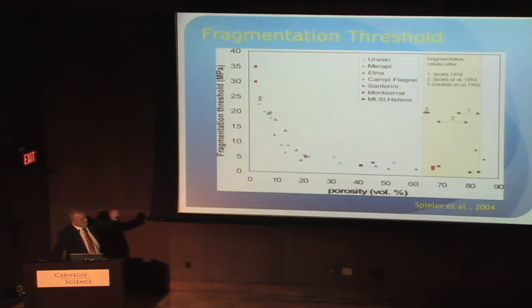So what science can we get out of it? What numbers can we pull out of it? First thing we can do is say how much overpressure do we need for one of these things to blow up, to produce ash. And here you see how much. And it turns out to be dominated by one variable, the bubble content of the liquid. And the bubble content of the liquid is the porosity. So on the left-hand side, you have solid rock. On the right-hand side, you have foams of up to 80% porosity. Okay, pumice. And you can see all the data points.